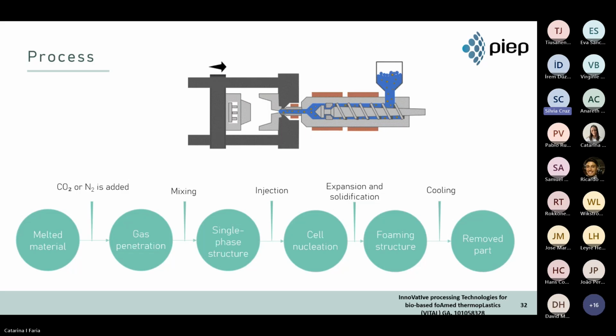The physical foaming variant requires the setup of an injection molding unit with an external physical foaming storage container. An additional control unit is necessary to timely regulate the amount of foaming agent introduced into the barrel under pressure, guaranteeing that the gas is at its supercritical fluid phase to properly mix with the polymer.